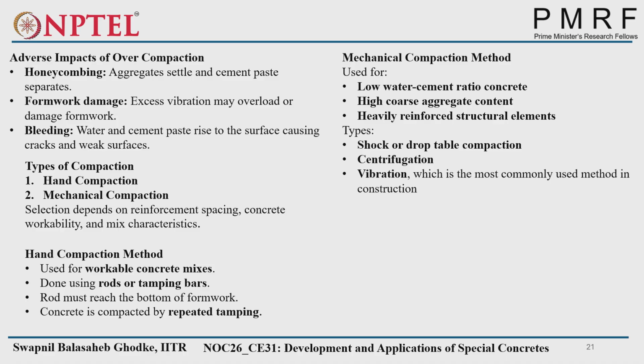But mechanical compaction is different from that one. Mechanical compaction is generally used wherever low slump concrete is there, like a low water to cement ratio, high coarse aggregate content, and heavily reinforced structural elements. For those purposes we need to give higher energy, and that is not possible with hand compaction. So that's why we are going with mechanical compaction.